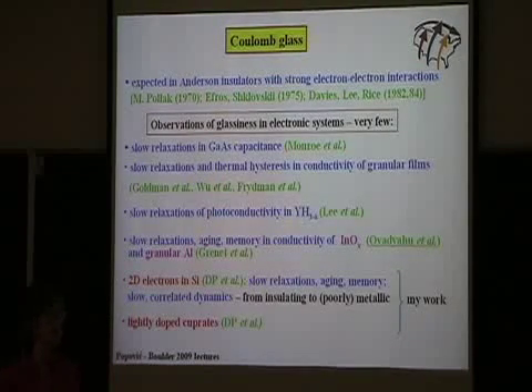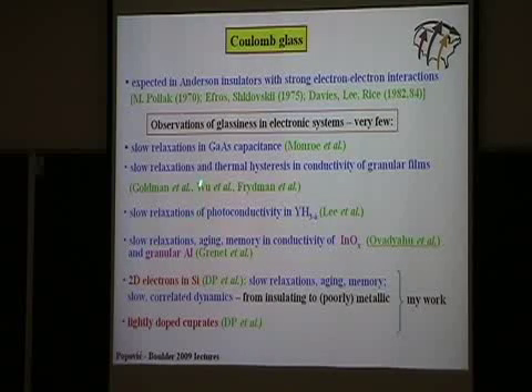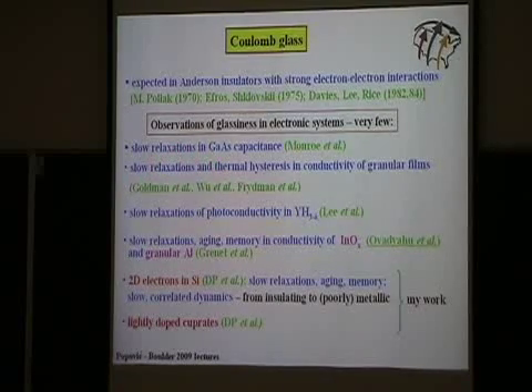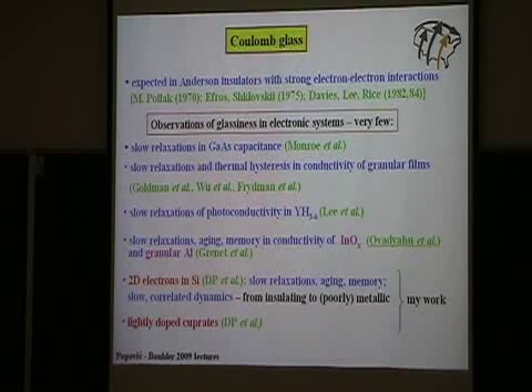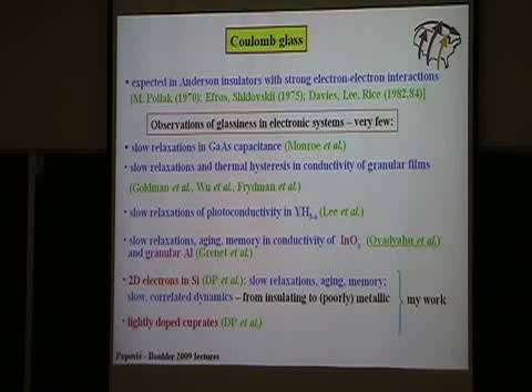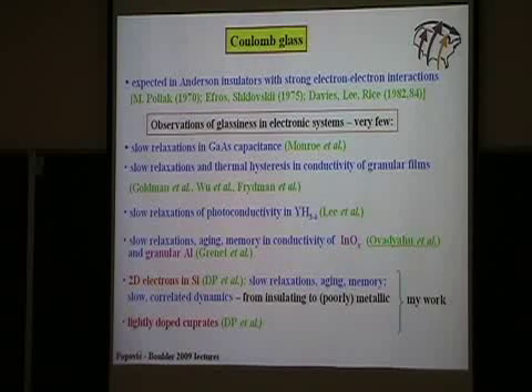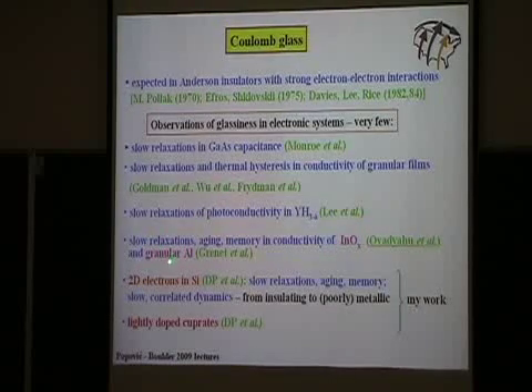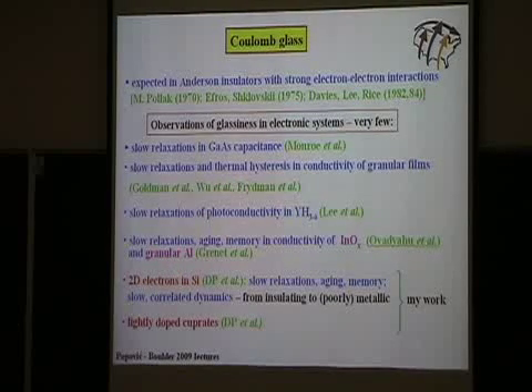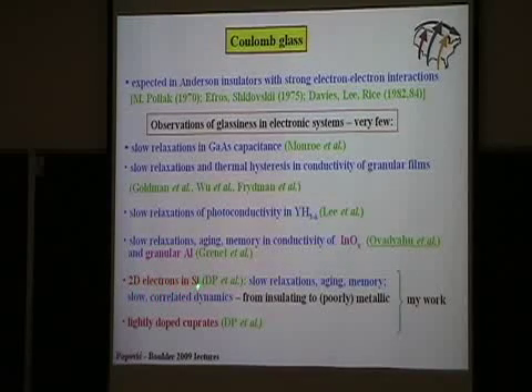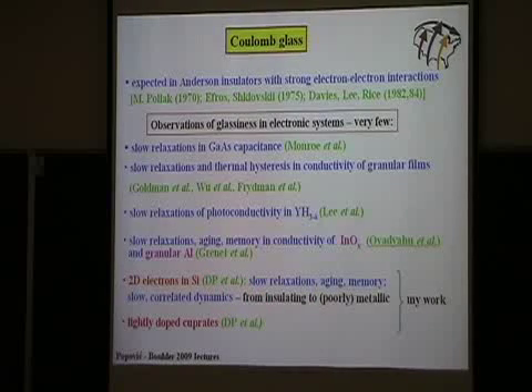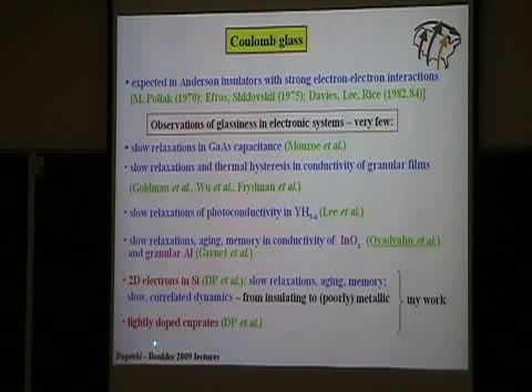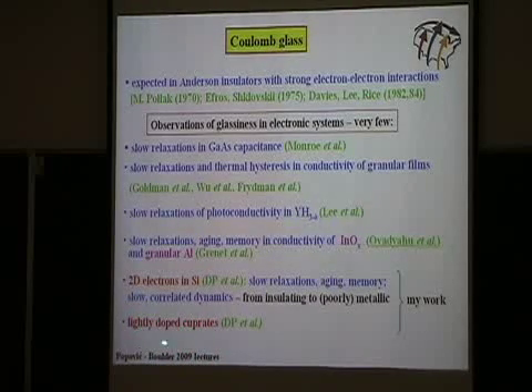However, there have been very few experimental studies of Coulomb glasses. There were a few early observations of slow relaxations in some semiconductors and granular films. However, these were really not pursued in much detail. Most detailed studies were done on films of indium oxide by the group of Ovadyahu. More recently, similar experiments were done on granular aluminum films. And also over the last several years, my group has done experiments on a 2D electron system in silicon, where we have found a number of signatures of glassiness, and I will describe these in the remaining two lectures. And also more recently, we have looked at charge dynamics in lightly doped cuprates.